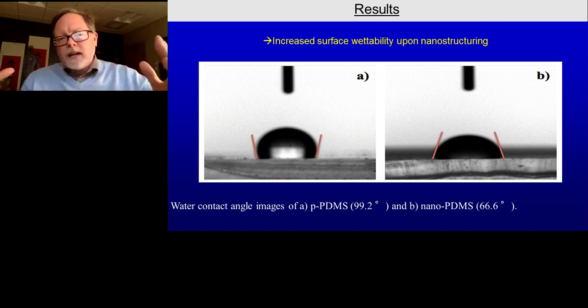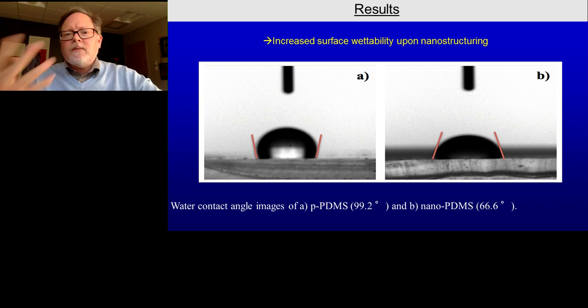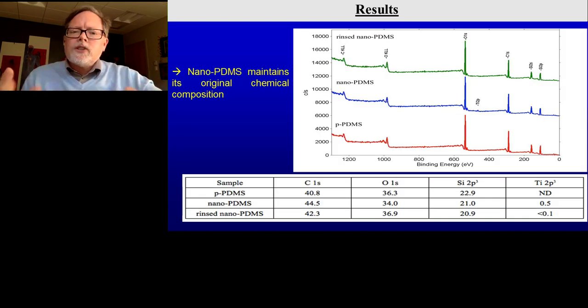Clearly you see a different spreading of that contact angle, again proving you can change wettability. You can change surface energy by simply employing nano-textured features. We also wanted to check chemistry. So without going into too much detail, we used XPS, X-ray photoelectron spectroscopy. We saw the same exact chemistry between the starting PDMS and the PDMS that had nanoscale features. This, again, important for the FDA to show similar chemistry, just changes in nanoscale feature.